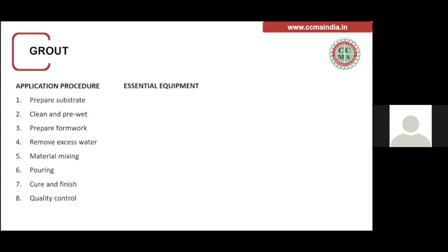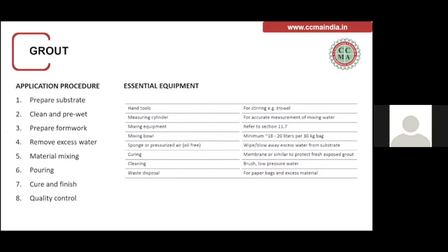Some essential equipment required during grouting are hand tools and a measuring cylinder. This is important because these grouts require water, and the water should be pre-measured. In general practice, we see that water is measured on some volume, like a mug or something similar, but that is not the right way of measuring water. So a measuring cylinder should be there so that the water content is measured properly. The mixing equipment should be proper, and some hand tools like a sponge or curing membranes should be there at the site.